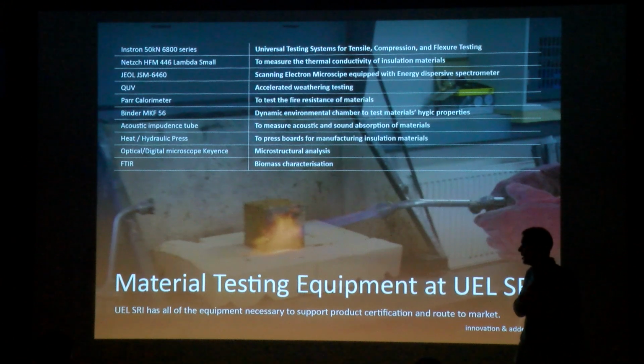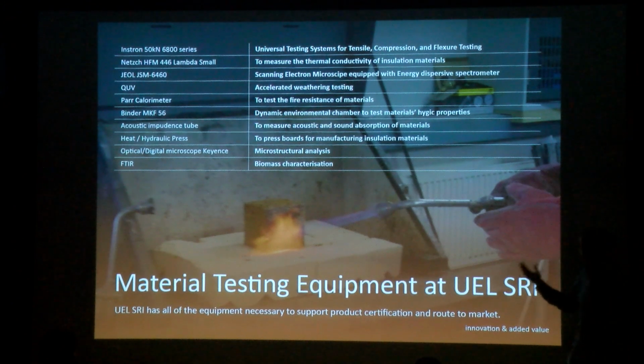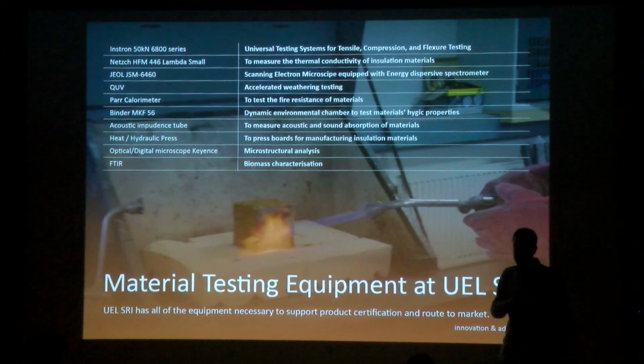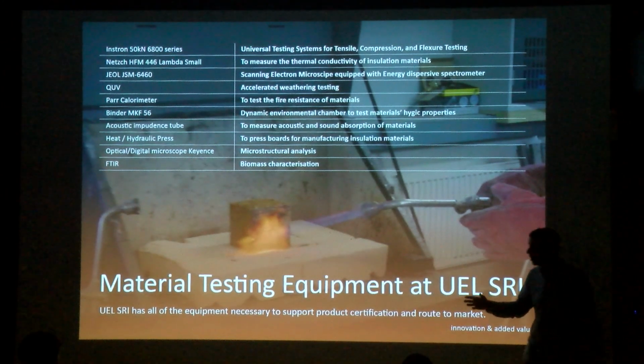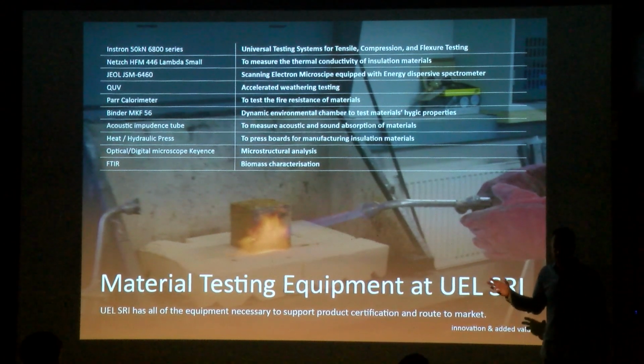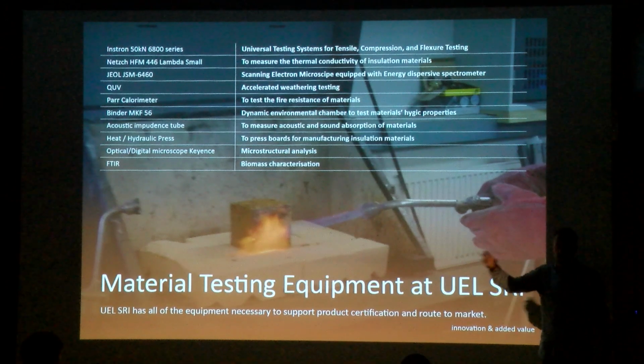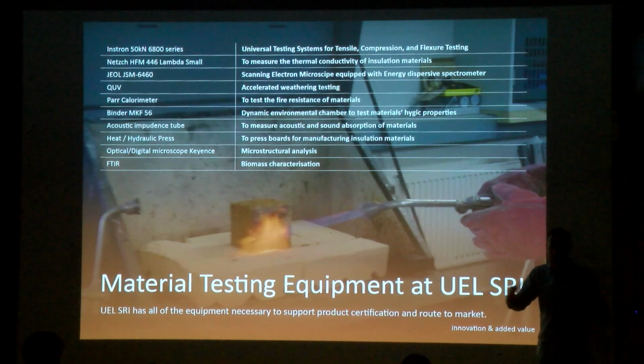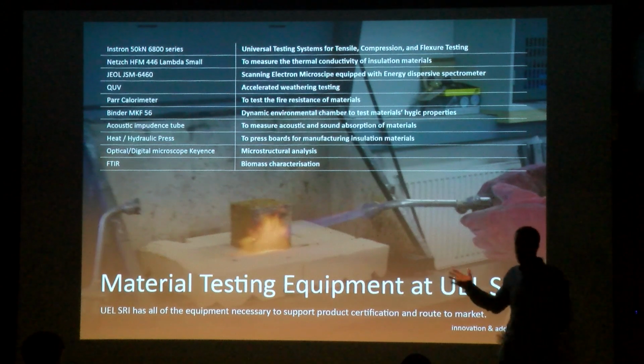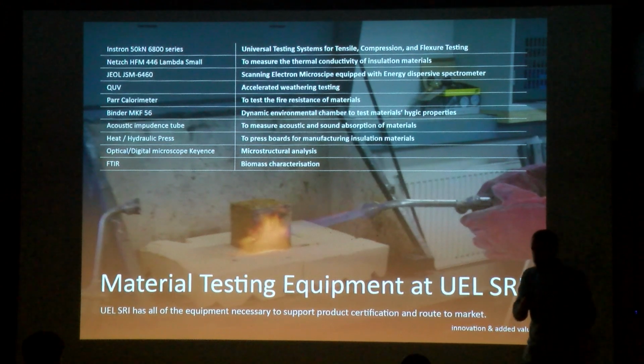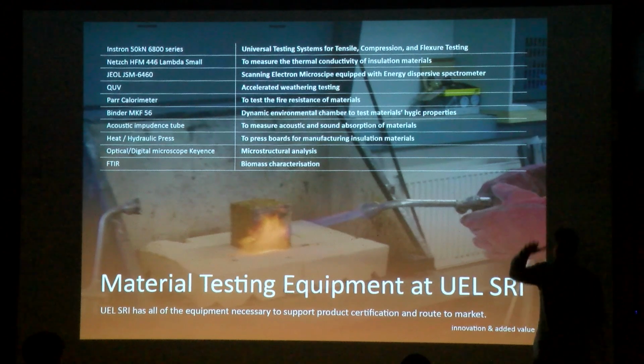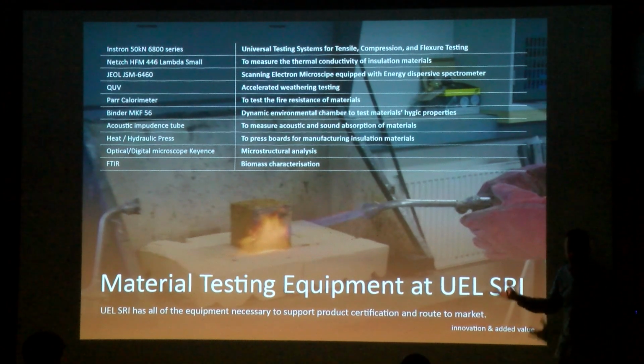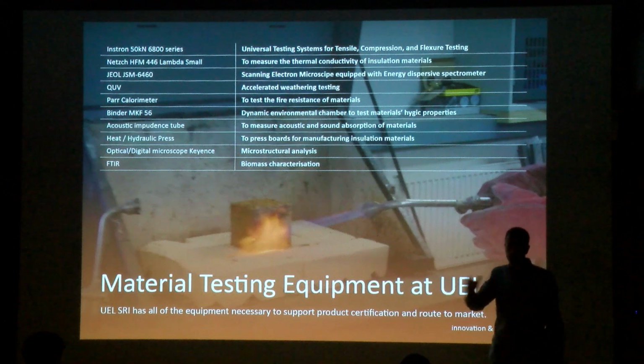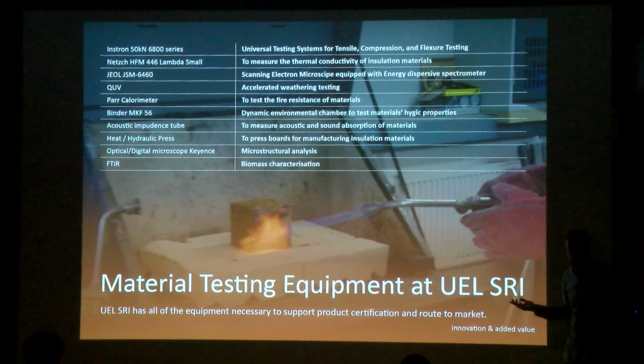And this testing is allowing us to go further and to support our partners. Most of the partners that we are working with don't have the capability to test to this standard. So we are doing the testing internally, working with bagasse that comes from different regions in the world. And then that testing is assisting them to do the verification locally. So instead of going blindly to a laboratory with different ratios and different samples, we are saying, do the sample with this ratio, utilize this pressure on the hydraulic press, and then you will get a sample that is going to pass your fire testing, so you don't need to do it 10 times. And that's proven very helpful.